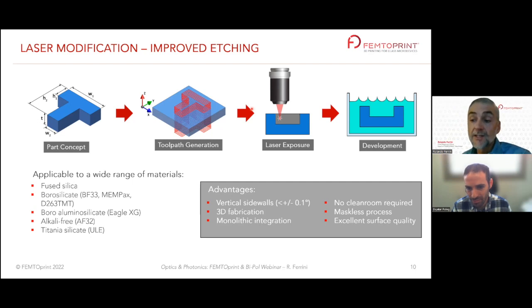What happens in the voxel is that this high power triggers 2 photon absorption processes. And the 2 photon absorption processes can have several consequences depending on the laser parameters. 2 typical consequences are either the fragilization of the glass or the densification, or both. If the glass is fragilized, that's exactly what we use to write into glass. That's why at the beginning of our story, we called ourselves a 3D printing company. It's more a 3D writing. With the voxel, we write into the glass and we fragilize the glass locally.